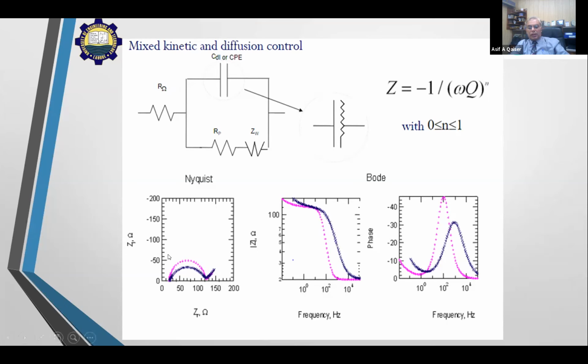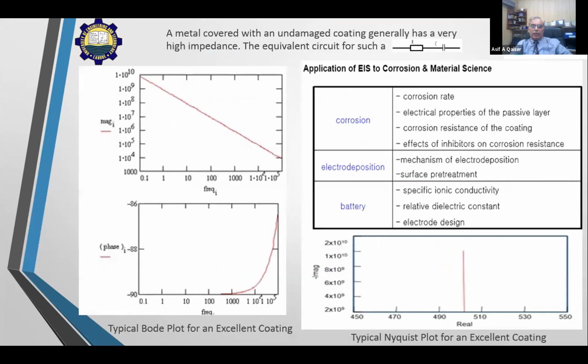So what is the result? You can see here this red curve is for a pure capacitor, and this purple is when we have the CPE. So as a result, when we have a pure capacitor, we have a perfect semicircle. But when we have this constant phase element, since the time constants are distributed, we have a depressed, distorted semicircle. There are many applications again of studying or applying this electrochemical impedance.